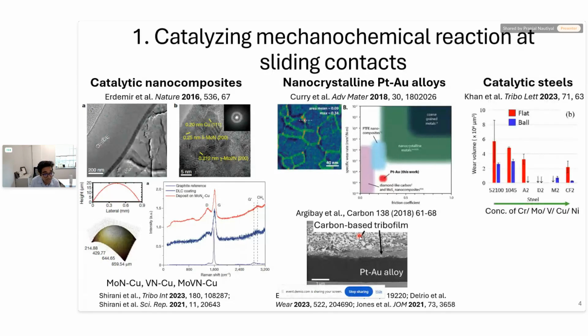Recently, researchers at Northwestern University extended this concept to design catalytic steels. So they designed steel alloys with higher concentrations of known catalytic metals like chromium, molybdenum, vanadium, copper, nickel, and pardon the abbreviations. There are all these abbreviations here, but essentially some of these compositions here labeled as A2, D2, M2, CF2, they contain higher concentrations of some of the transition metals that are known for their catalytic properties. And as you can see on this plot, the wear volume is negligible for some of these compositions, as opposed to the 52-100 steel, which is the bearing steel, and which does not contain very high concentrations of these catalytic metals. So clearly, these catalytic elements, they improve the wear resistance of the steel.